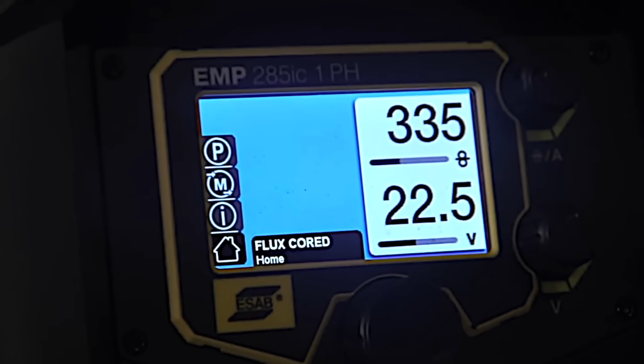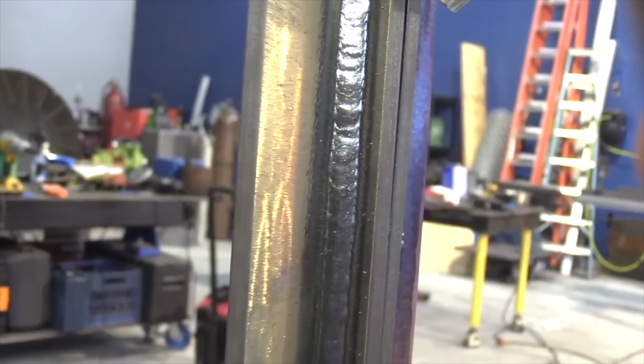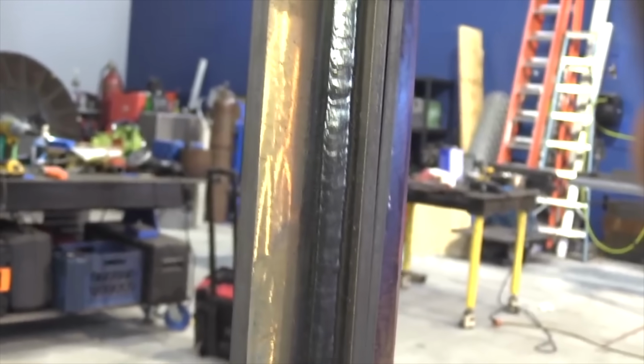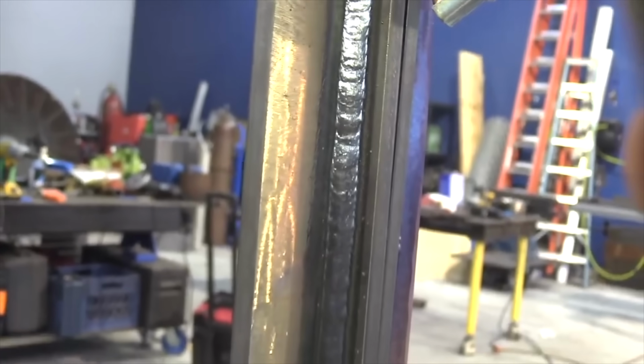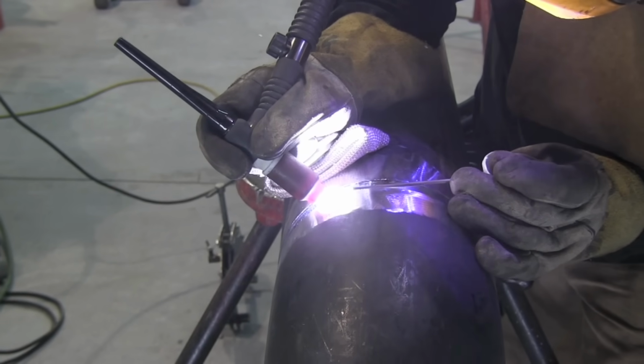Dual shield flux core is an awesome process. You can go uphill, and you can go uphill really hot with hardly any torch manipulation and still get a good sound uniform bead. Very little manipulation right here, just almost none, and still comes out flat, uniform, not overly convex, and you just can't do that with short circuit MIG. Dual shield flux core also burns through mill scale a whole lot better than short circuit MIG.